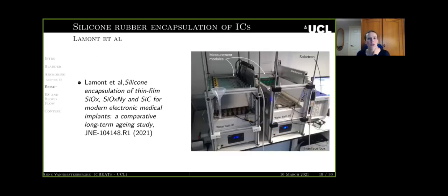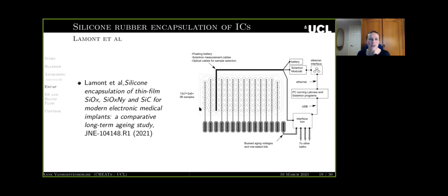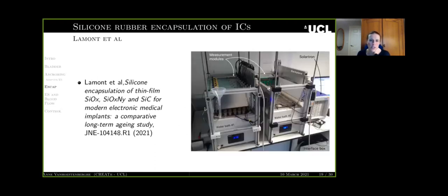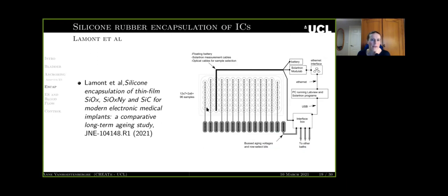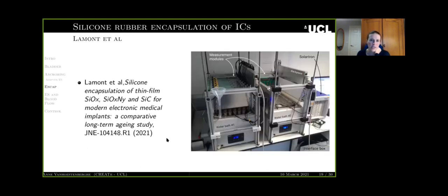This is the picture I showed you earlier. This is our test bench, and in a simplified version, what you can see is that every single one of these holes holds one sample in its own water bath. It's kept at a constant temperature. Each of them has its own water content, so there's no contamination from one to the other. And we can apply a bias to all the sensors. So we have 96 samples per bath, and we have a series of baths at different temperatures. These two show you the 66, 67 degrees test. They are regularly tested with electrical impedance spectroscopy using a Solartron system.